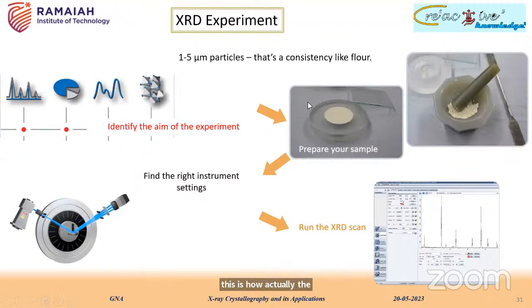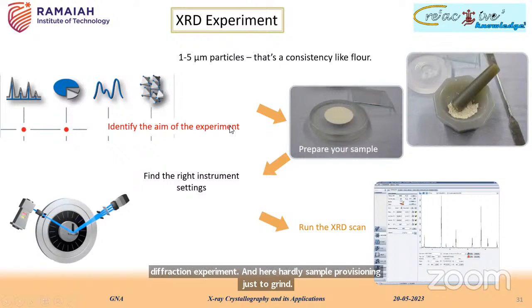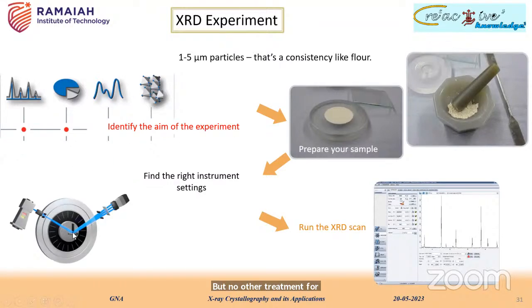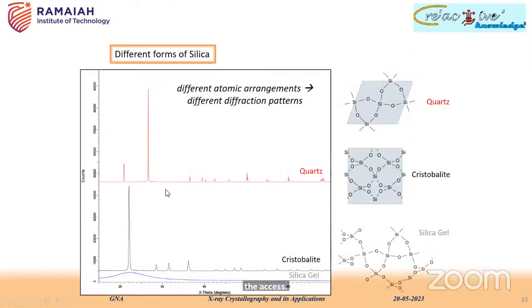It's a very simple technique, the powder X-ray diffraction method. You take the sample, grind it thoroughly to make a very fine powder, and then subject it to the powder diffraction experiment. Sample preparation is just grinding, with no other treatment. You place this powder in the sample holder, pass the X-rays, and record the scan. This technique is very efficient and very quick, and we are able to quantify and also identify the crystal system properly.